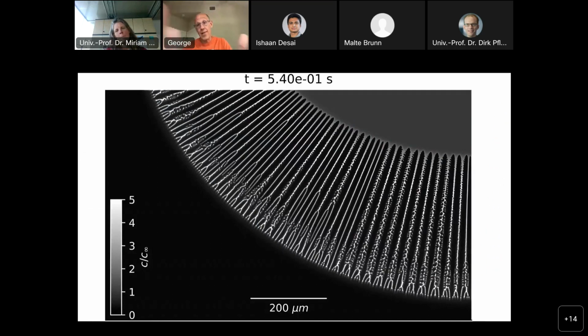The other half of the melt pool is to the right, but we use symmetry boundary conditions in this part. And here what you see is solid metal. These are alloys, so these are mixtures. This is a nickel aluminum alloy, and there is composition variation, and this is a kind of metric of the composition, which is also important for the properties of the final material.